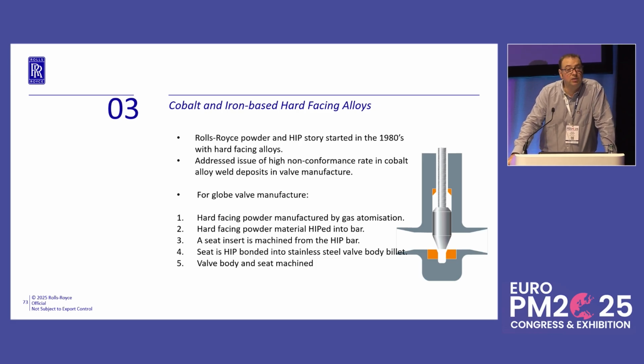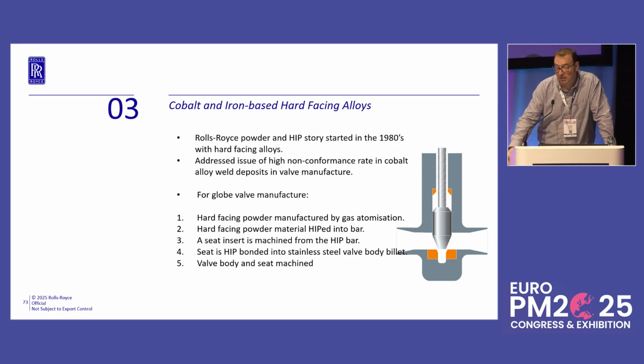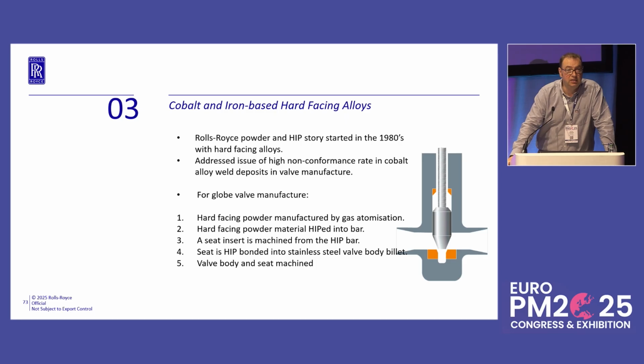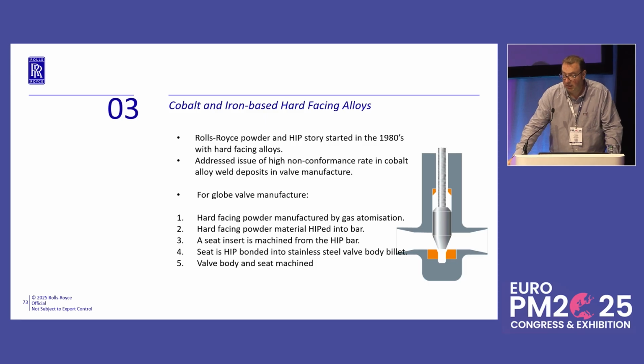What they did was they introduced a two-stage process based around powder and HIP. In the first part, we create a bar out of powder HIP. We take the powder, in this case Stellite 6, a cobalt-based alloy, and it's consolidated into the bar. The bar is decanned, and then they take slices from that bar. We then take a billet of steel, something like 316 austenitic stainless steel, and you drill the bore into it. You then drop the hard facing in, put the plug in, seal it, evacuate it, and then it goes back into the HIP vessel, where we use the HIP to drive the diffusion bond between the hard facing and the structural steel. Once that's complete, you can then machine the final component from the billet. Try and remember that, because we're going to come back to that in just a couple of slides' time.